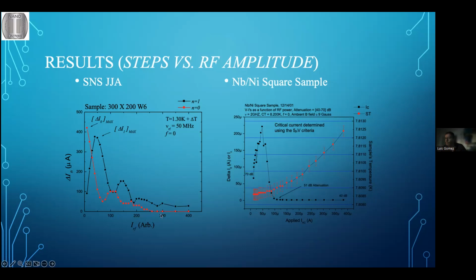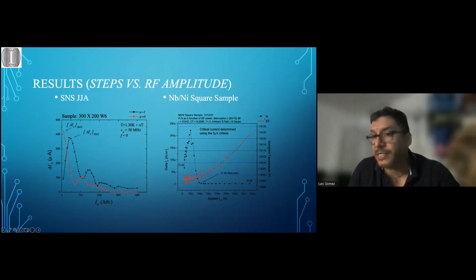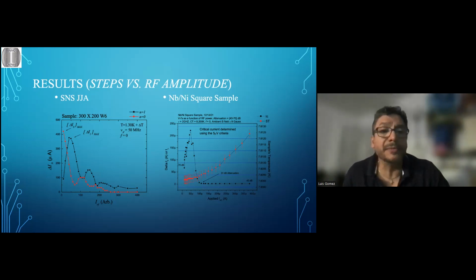So this is the characteristic of many measurements done at different values of amplitude, and this is the same one for here. Actually, this red curve is not the same as this one. This red curve represents the temperature of the sample thermometer. Maybe I should have changed the colors so as not to cause confusion. This is just how the critical current, the zero step, changes with the applied RF signal. Here the frequency is fixed, but the amplitude changes during the measurement.